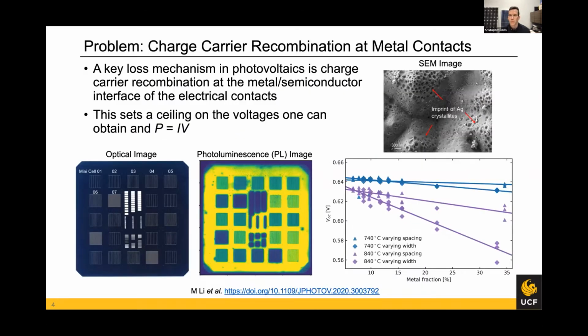So one of the key problems is when you put metal on a semiconductor, it forms defect states. So those charge carriers tend to recombine, so you lose them. You don't get the current and voltage associated with those carriers. So that's a problem. So we've actually studied this quite a bit.